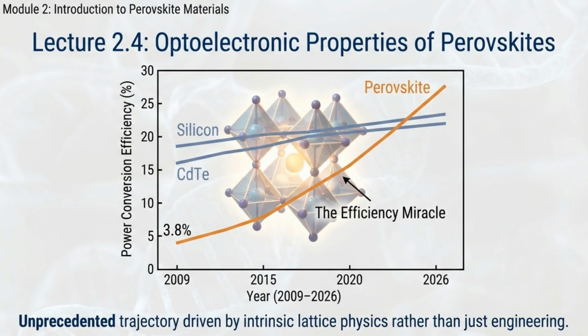In 2009, the first Perovskite solar cell achieved a meager 3.8% efficiency. In just over a decade, it shattered the 26% barrier, rivaling the absolute best silicon devices ever manufactured. What makes this trajectory truly unprecedented is that early Perovskite films were not perfectly engineered single crystals. They were messy, defect-ridden, solution-processed films made in basic chemistry labs. The fact that they performed so brilliantly proves that their success is not just a result of clever device engineering. It is fundamentally rooted in the intrinsic, incredibly forgiving quantum physics of the Perovskite lattice itself.